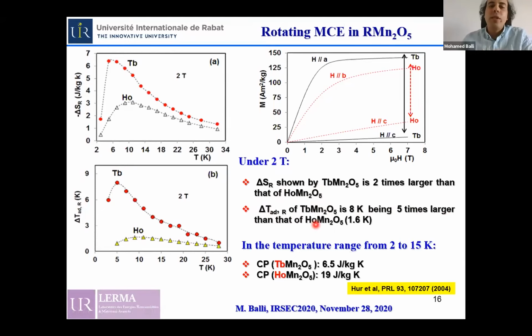It is also worthy to mention that the rotating adiabatic temperature change shown by terbium compound is more or less 5 times larger than that shown by garnet materials usually used in magnetic refrigeration at low temperatures. This will open the way for the implementation, particularly of terbium compound, in cryogenic magnetic refrigeration.